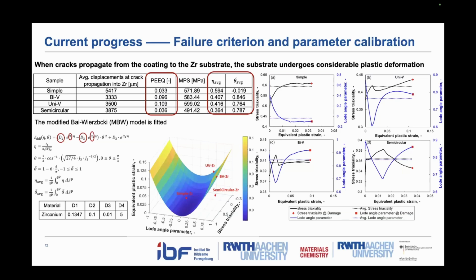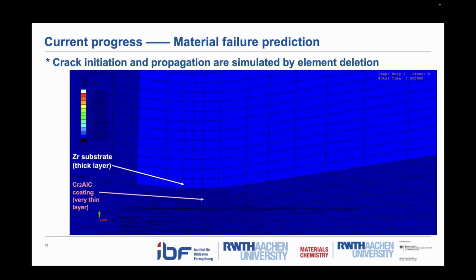So now we have identified how our samples failed, and what kind of failure criterion we should adopt, and also we calibrated the parameters. So we run the final round of simulation, and we replicate the material failure that we observe in the experiments by element deletion. So here shows a video.